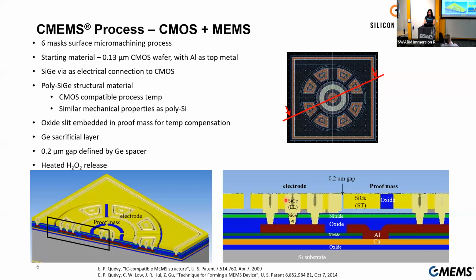Between the proof mass and the electrode, we define a 0.2 micron transducer gap using the spacer deposition. And underneath the structure, we use germanium as the sacrificial layer. During the release process, we put the wafer into heated peroxide solution. Then the germanium spacer and the germanium sacrificial layer will be removed and the structure can be released.